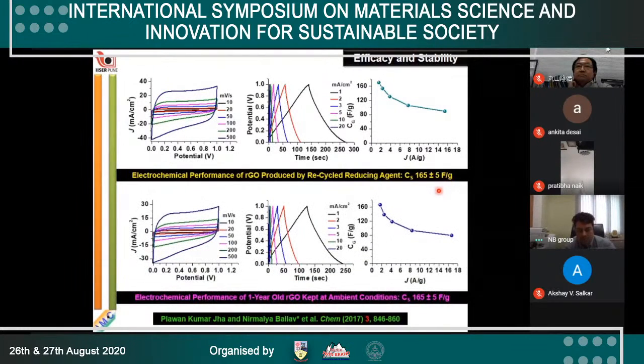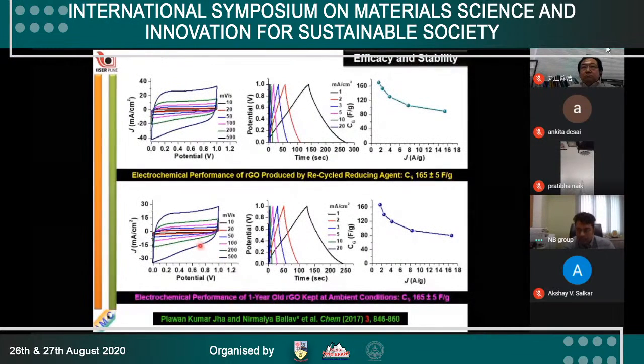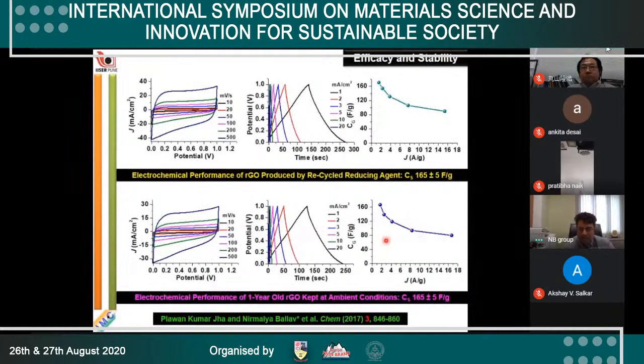You can even keep our RGO material for a long time. We have kept RGO at ambient conditions for more than 1 year and evaluated the supercapacitor performance. Now if we compare this performance with a newly prepared RGO material, again the capacitance values are within plus minus 5 farad per gram. So indeed, our RGO material is a very stable material and a quality material.